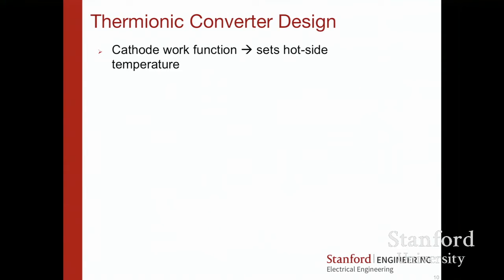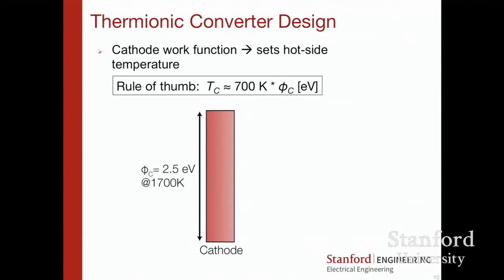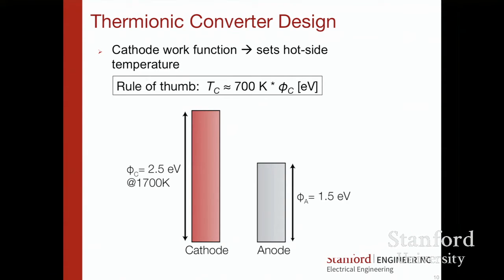In any event, the cathode work function is designed around the hot side temperature. There are different sources of heat. I'll mention some completely green ones, concentrated solar. There would be not so green ones that this might help in terms of efficiency, and there's a sort of 700 Kelvin times the work function in electron volts. So 1700 Kelvin, you subtract roughly 300, is a hot flame, that torch. And so you have a work function around 2.5 electron volts. That's rather easily achieved. The anode at 1.5 is not so easily achieved. And I'll mention where we are in that.